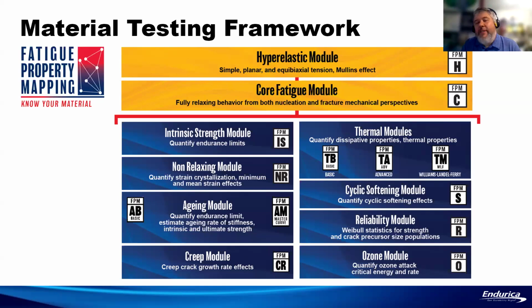The core fatigue module is where we measure the fatigue crack growth rate curve under fully relaxing conditions. We also measure a few points on the strain life curve. And from those 2 experiments, we can determine the initial crack precursor size of the rubber. So those are the 2 required experiments. Depending on your application, there are all sorts of other things we can think about.